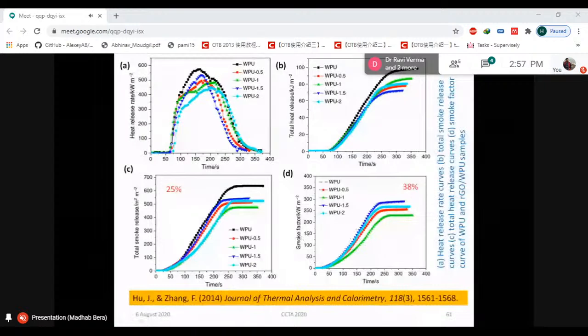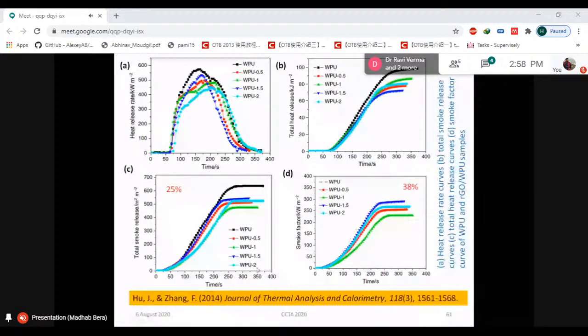In another work, Hu et al. investigated the heat release rate of water-based polyurethane by adding various weight percent loading of functionalized graphene. The heat release rate and total heat release density are also decreasing with the addition of up to 2% functionalized nanosheet, decreasing up to 25%, and the smoke factor is also decreasing up to 38%.